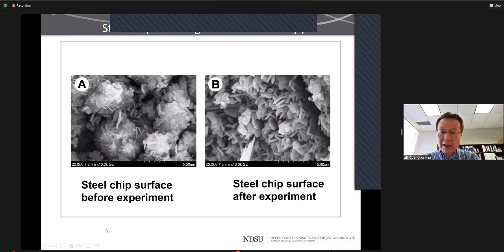And in order to verify our hypothesis, we performed some microscopic scanning using SEM technology, scanning electron microscopy, to look at the steel chip surface before and after the treatment. Figure A shows the steel chip surface before the experiment. As you can see, there are lots of crystal forms on the surface. Those are the iron oxide formed by iron and oxygen. And after treatment, we found a high density of rod-type bacteria. So therefore, we verified E. coli bacteria can be effectively attached to the steel surface.